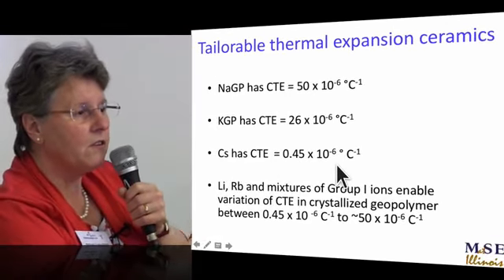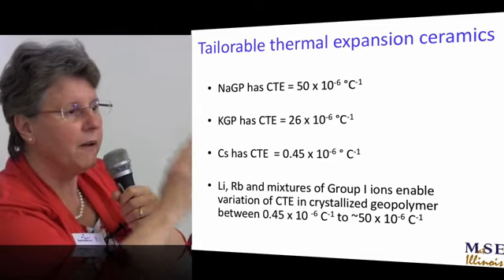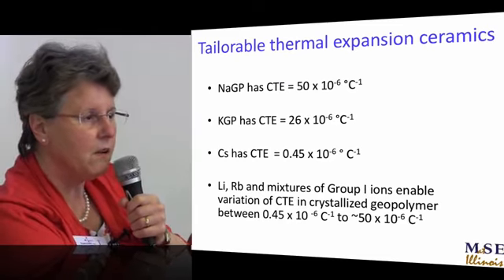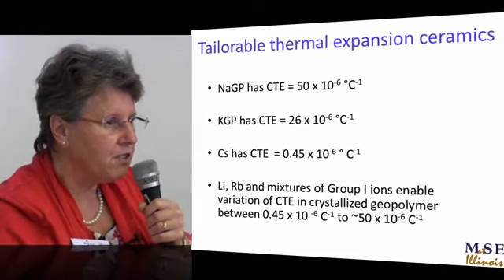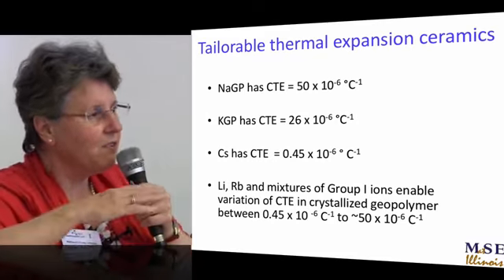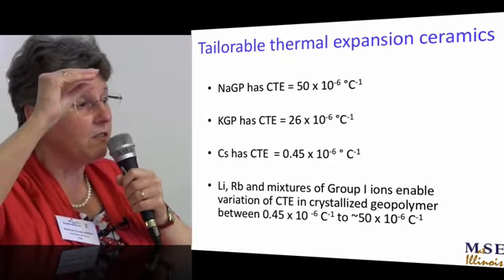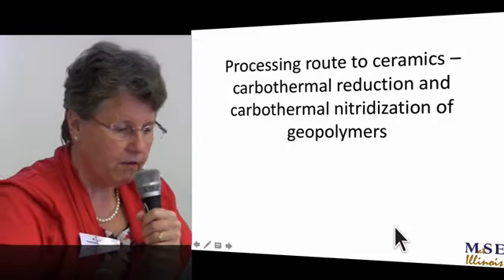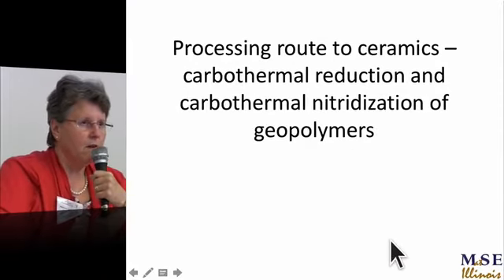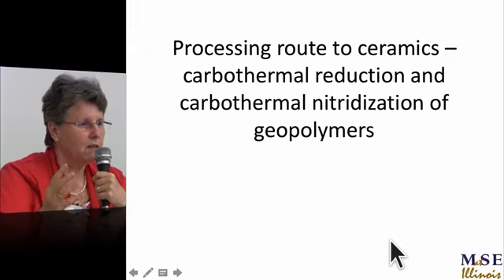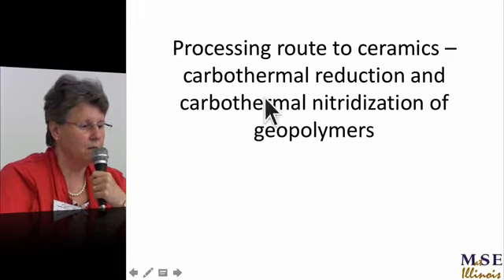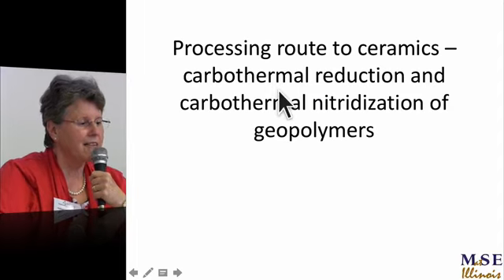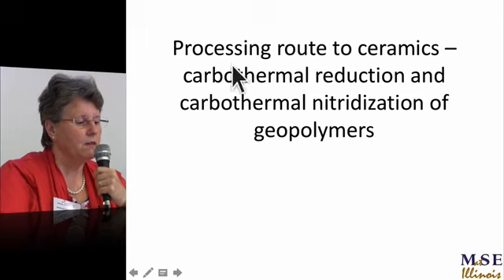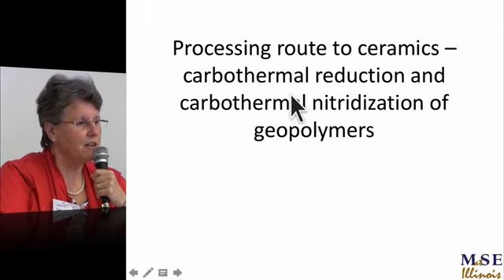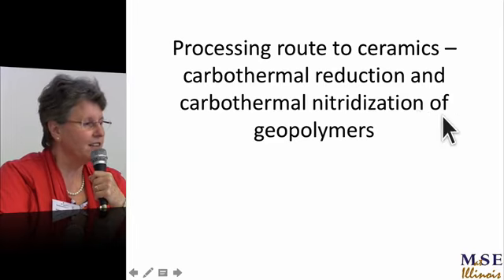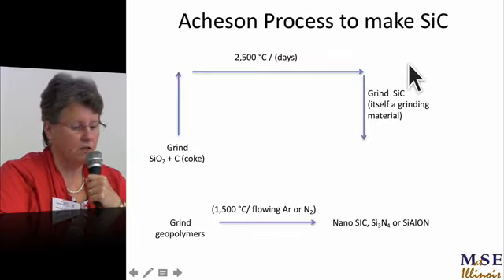So now, if you can start tailoring the thermal expansion: make a geopolymer coating on a metal, figure out what the metal thermal expansion is, whip up a mixture with a similar thermal expansion, and they'll all expand together, see? So yeah, we're working on that too. It works. Now that's like heating a geopolymer to make a ceramic. Here is heating a geopolymer to make a ceramic powder, and this is called carbothermal reduction and carbothermal nitridization, and it's a way to make ceramics cheaper.